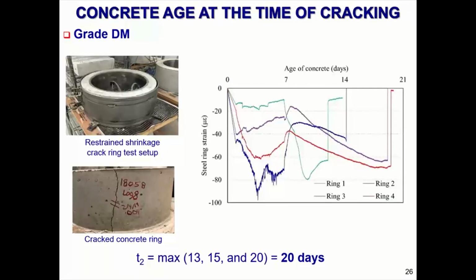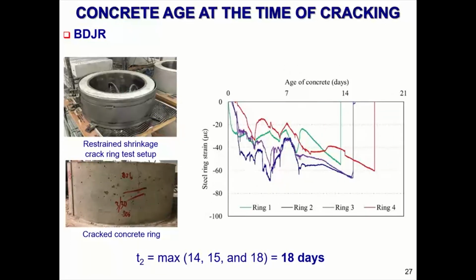We also looked at concrete at the time of cracking. Grade DM cracked at 20 days, so we wanted to make sure that the concrete had cracked before we placed the thin epoxy overlay. And for our grade BDJR, it cracked at 18 days.